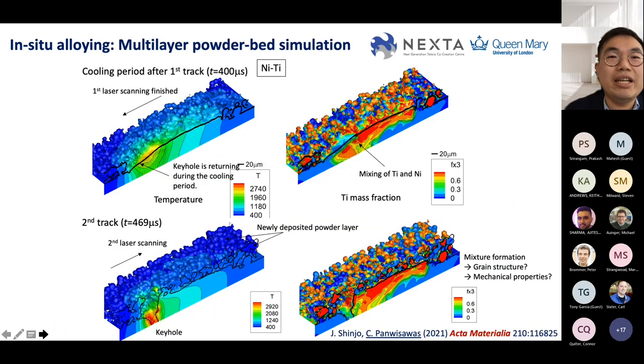And then once we implement this in a multi-layer powder-bed simulation, you will see that now we don't have only a single material. We have nickel 50%, titanium 50% spread onto the bed. And then we can actually see how things mix together. And if you choose the wrong parameter, you will see very clearly that the mixing is not very good. And that is why defects emerge or form. And then you see after the second deposition, at this process condition, the mixing seems quite good. But the question after this is, how can we use this information further for microstructure development and property prediction as well?